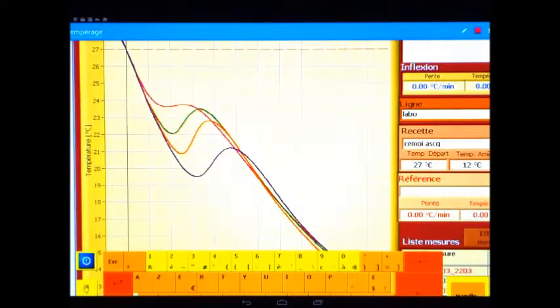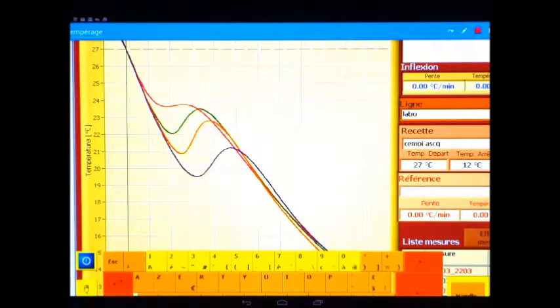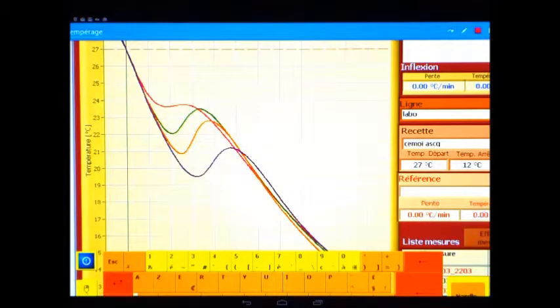This is an exercise to temper a dark chocolate to form a shell. These three curves give the information that we have a small amount of crystals. In fact, they were ideal for the shell because we used to have very specific cooling and solidification conditions. In this case, the plateau gave very bad results.